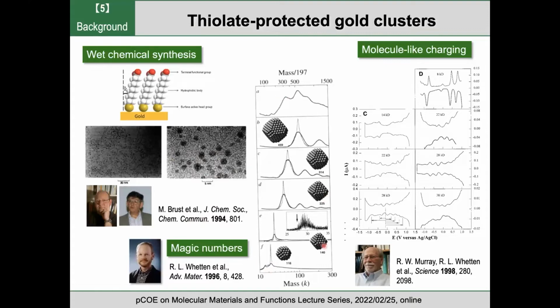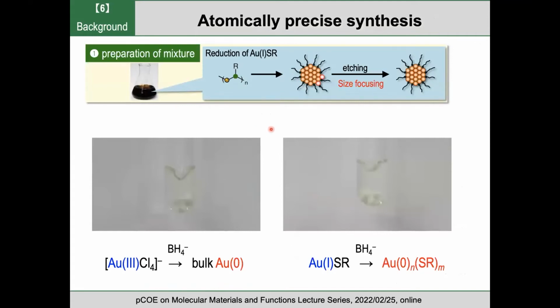And here is the mass spec of the isolated gold thiolate clusters. So we know there is a series of magic species by this important work. And also Professor Whetten and Murray reported the molecular-like charging of small thiolate-protected clusters. So this is the evidence that the clusters have molecular-like electronic structures. So inspired by these stimulating works, we tried to establish the atomically precise synthesis of ligand or thiolate-protected gold clusters.